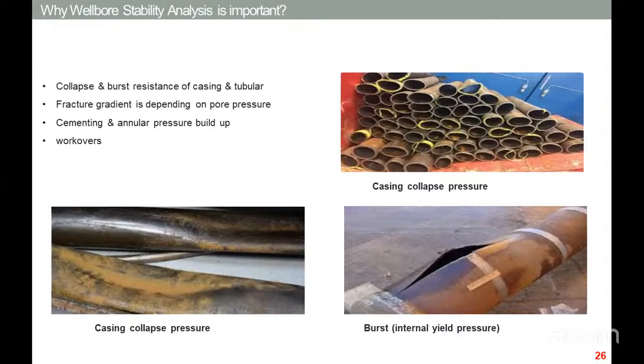Why is wellbore stability analysis important? This is showing the casing collapse pressure, burst, casing collapse. This is what happened on the casing of the well. This is real. Wellbore stability directly influences casing design and mud program planning. Proper estimation of the pore pressure and fracture gradient prevents catastrophic failures like blowout, stuck pipe, and well design problems. Geomechanics ensures casing integrity.